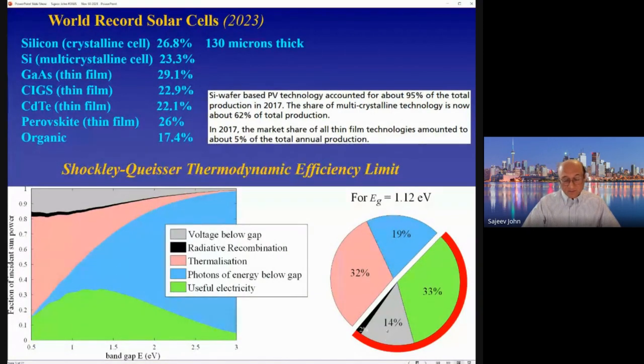There's also some thermal effects associated with entropy that reduce the voltage. That's this gray region. And so Shockley and Queisser predicted that the maximum possible efficiency of a silicon solar cell at around room temperature is slightly below 33%. And that is assuming that all of the light from the sun that impinges on this silicon solar cell can actually be absorbed over the entire 300 to 1200 nanometer wavelength range.